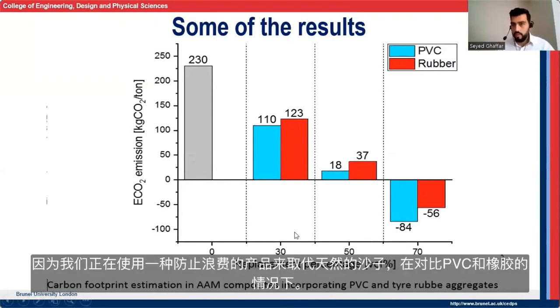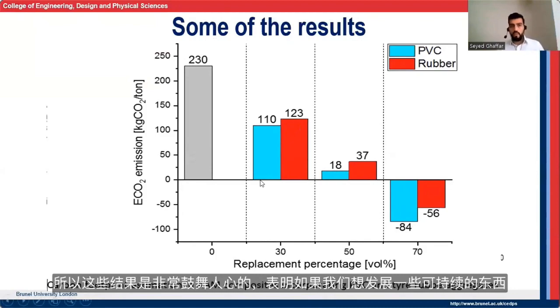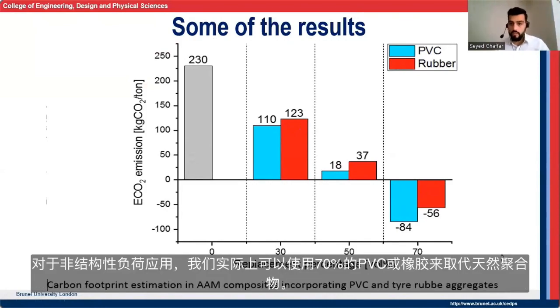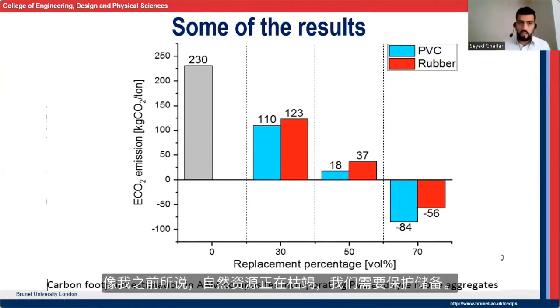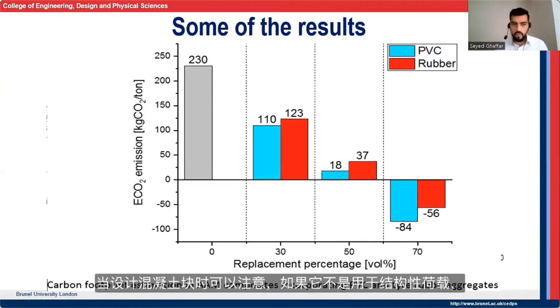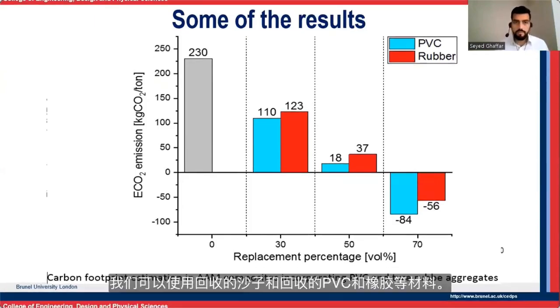So because we are using a waste-driven product to replace the natural sand in the case of PVC and rubber, these results are very encouraging, showing that if we want to develop something sustainable for a non-structural load-bearing application, we can actually use 70% of these PVC or rubber to replace the natural aggregates. And as I said, the natural resources are depleting, and we really need to reserve them. We need to be careful when we design a concrete block which is not for structural load-bearing applications. We can use recycled sands, recycled aggregates, such as PVC and rubber.